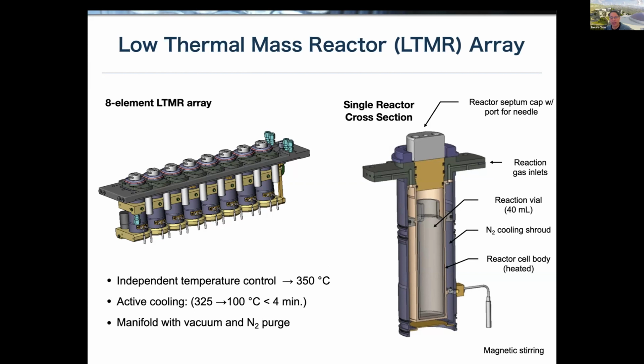And that's really important because nanoparticles don't stop growing when you get to the size that you want them to grow to. You have to really shut down that reaction very quickly. And in this case, we use a shroud of nitrogen gas that quickly cools this vial.